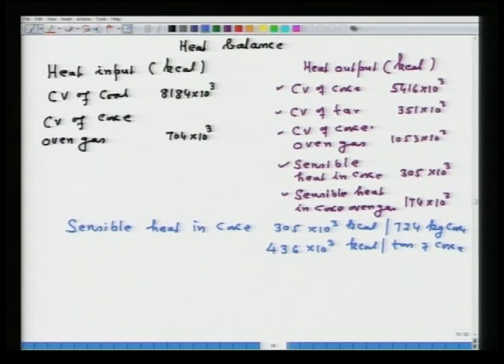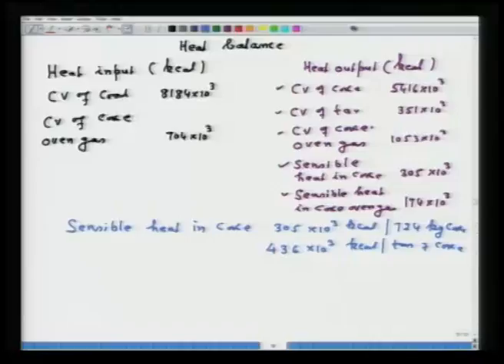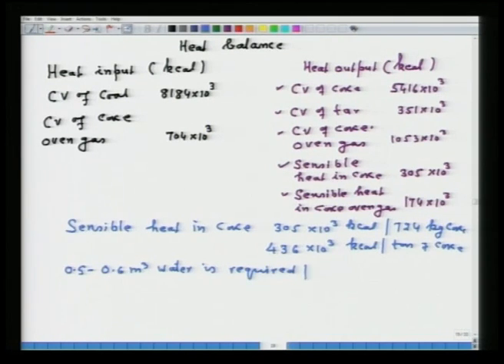What happens on wet quenching? This energy is lost. So, what you are doing on wet quenching, one thing is that you are losing the sensible heat, that is okay, but the second thing is that you are harming the environment. You are using a very large amount of water, approximately 0.5 to 0.6 meter cube of water is required per ton of coke for wet quenching.